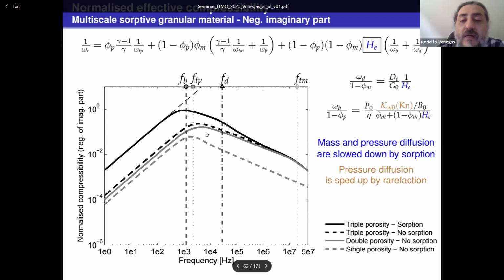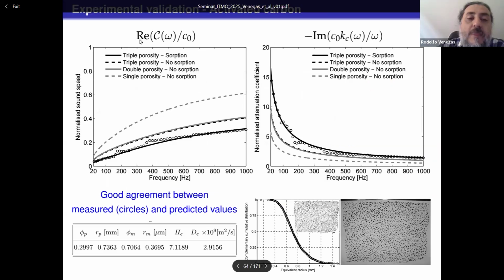Also, when we look at the imaginary part, we have different peaks now, and these peaks are related, one to pressure diffusion, another to heat conduction around the grains, and another one to mass diffusion. So what sorption does is to enhance the dissipation and also slow down some of these diffusion processes. So instead of having a peak at higher frequencies, sorption makes them go into lower frequencies. And that is very convenient because we can see that the effective speed of sound's real part is well predicted by the model, and that's a comparison with measurements, and is much slower than the effective speed of sound in a material with, let's say, grains that are completely solid, a single porosity material with no sorption, as shown here, and that translates onto the attenuation